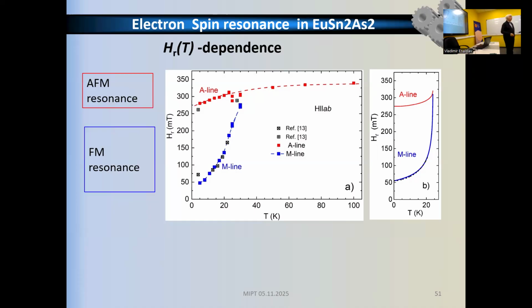Can you extract defect concentration from this magnetization fit? It affects only the amplitude of the effect, but here I plot the resonance. We assume that all the defects are independent. They're indeed independent from the measurements. They don't interact with each other. So it affects only the amplitude, which I don't plot here.